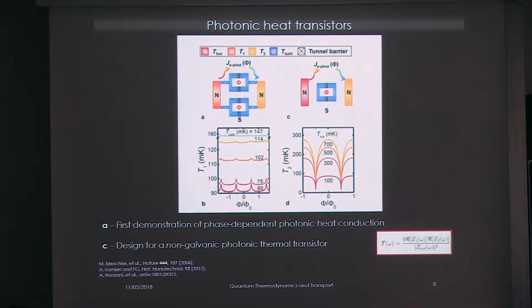So up to now, there were a few experiments on this. The very first experiment in coherent caloritronics dates back to 2006 in the group of Jukka Pekola, okay, where they used exactly this photonic thermal transport, showing how two reservoirs, normal metal resistors, let's say, residing at different temperatures, at a sufficiently low temperature, can exchange heat thanks to the coupling with the environment that is mediated by these two SQUID structures in parallel. So by changing the flux, you change basically the Josephson current of these devices, so the Josephson inductance of these two objects here, so they can be treated as inductors, okay? And so by doing this, you change the impedance of the system, and so you change the amount of heat transfer from one part to the other. So you see that there are very nice temperature oscillations in the system from one part to the other, okay?